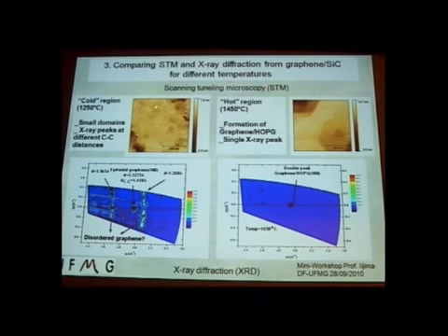What we decided to do is an X-ray diffraction analysis to understand the defects that are formed on this epitaxial graphene. Showing the two ends of the same sample, what we observe here is that several domains are formed, and these could be rotated domains with respect to the substrate. In the very beginning, where you have only a few graphene sheets, this is not a single domain graphene.